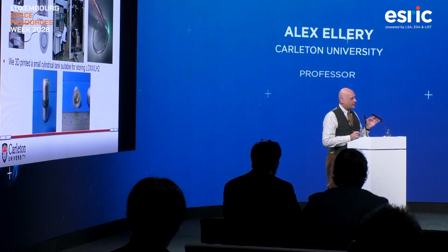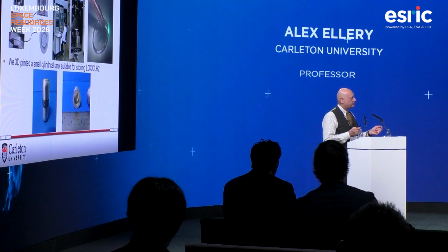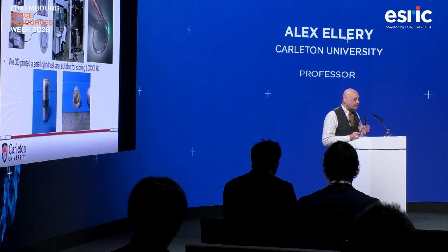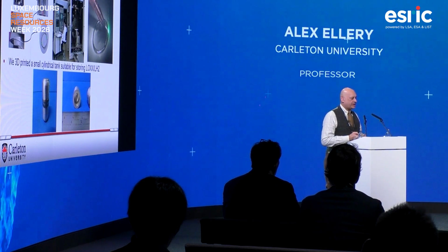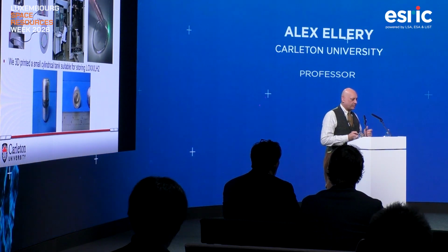So there was a break in the chain, but it illustrates that because the 95% pure aluminium we produced was too brittle to draw into wire, and because we were using EBAM, this was necessary, and that was the break in the chain.